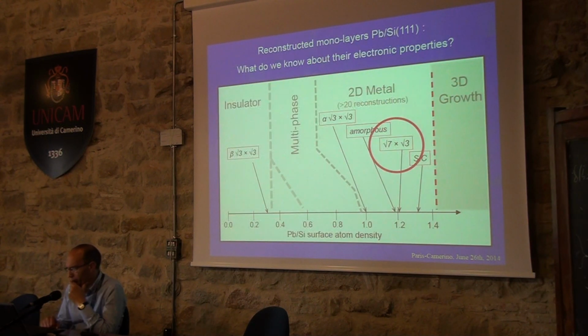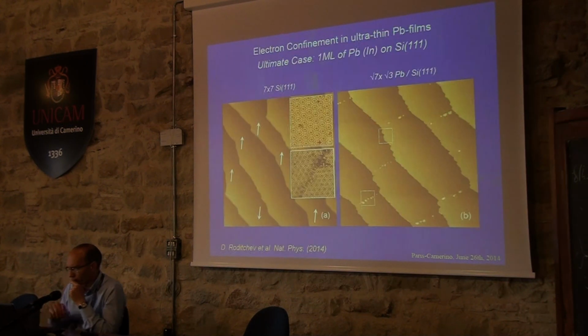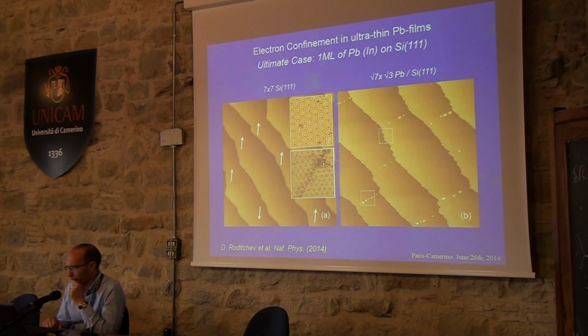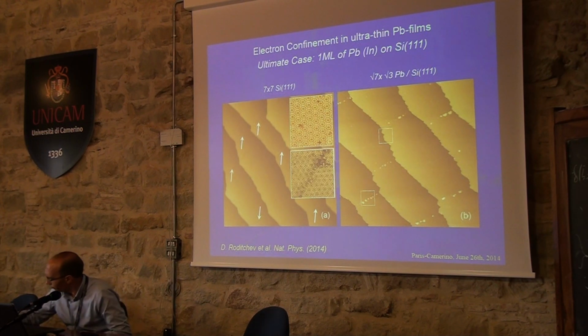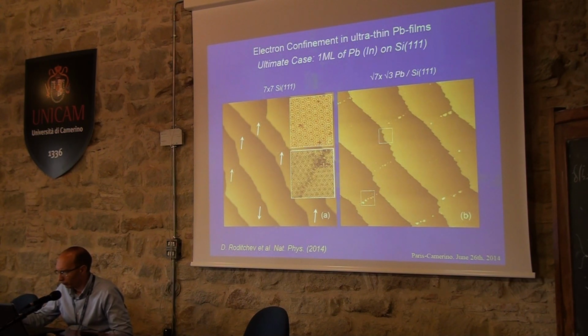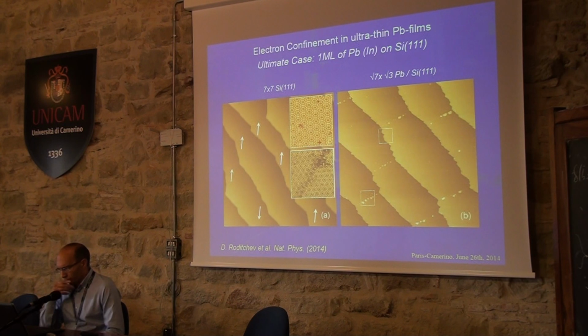Next slide. So, now I turn to the superconductivity on square root 7 by square root 3. Next slide. As I told you, these are atomic layers, and you really need to control the structure on the atomic level. First of all, you have to be sure that the material on which you deposit your lead is perfectly reconstructed 7 by 7 silicon, because otherwise you will have no stabilization of square root 7 by square root 3. So here on the left panel you have an atomic resolution image and a large scale image of silicon with atomic steps that you see.